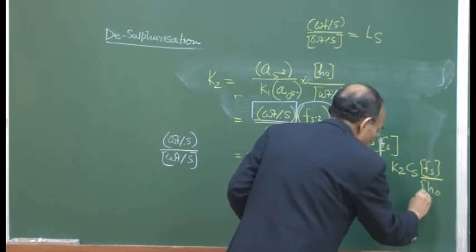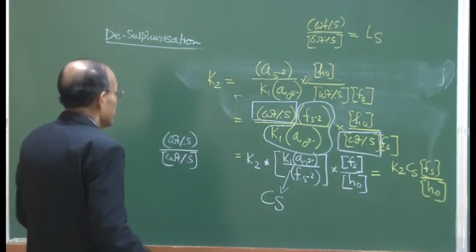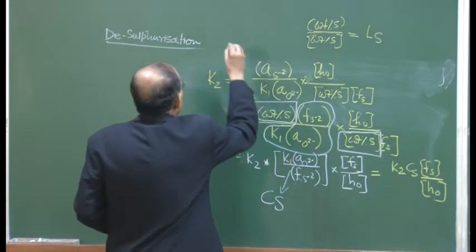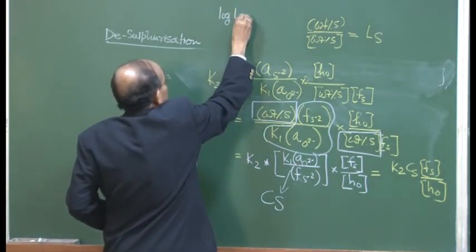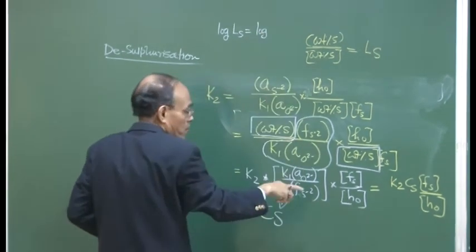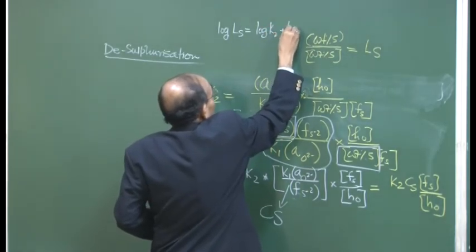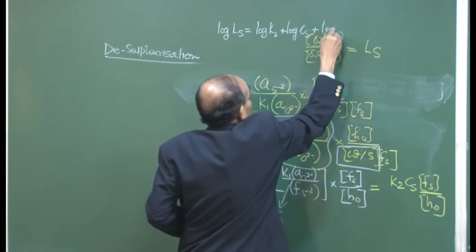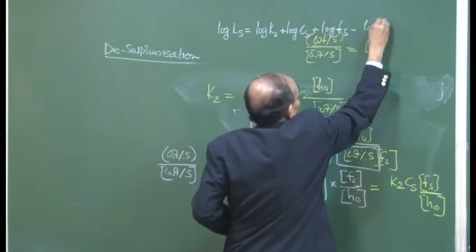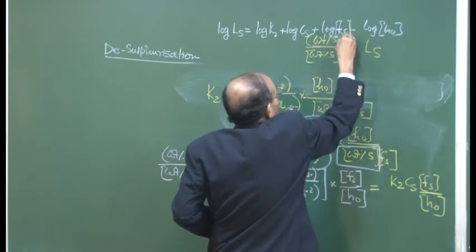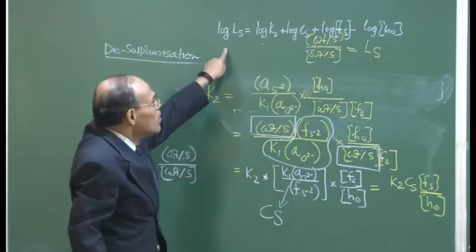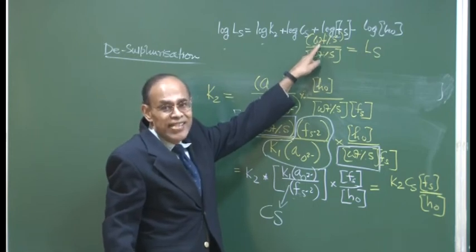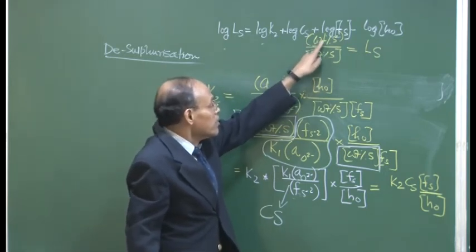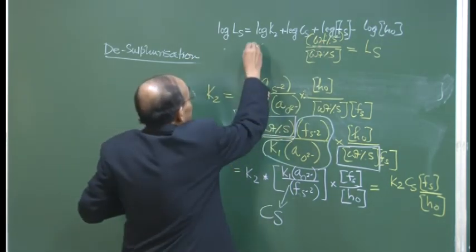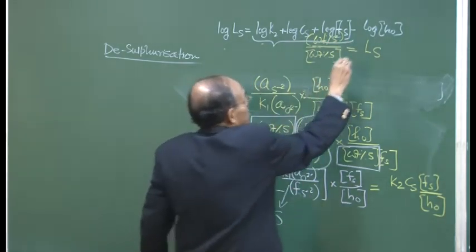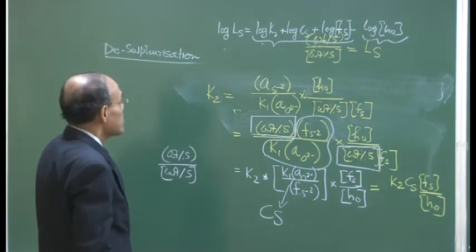divided by HO. And if you take logarithm on both sides, then you get the final expression for the partition coefficient: log LS is equal to log K2 plus log CS plus log FS minus log HO. What this indicates is that these are the three parameters which increase what we are looking for. We try to have the maximum sulfur in the slag itself, okay. To obtain the maximum value of the sulfur in the slag, maximum removal of sulfur in the process, we understand that these three parameters must be as high as possible, and this parameter which is presented by a negative sign must be as small as possible, okay.